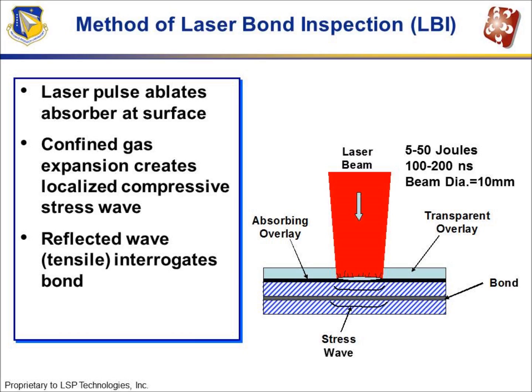What happens is that the laser beam comes through the transparent water overlay, is absorbed by the opaque overlay, a plasma is created and starts to blow off. The water overlay temporarily contains the plasma and intensifies the shock wave that is then produced as the plasma blows off. This directs the compressive wave to travel forward through the composite material, through the bond line, to the back free surface of the material. At that point, because of the impedance mismatch between the composite material and the air, you get a reflective tensile wave, not shown here, which comes back through and it interrogates the bond line.